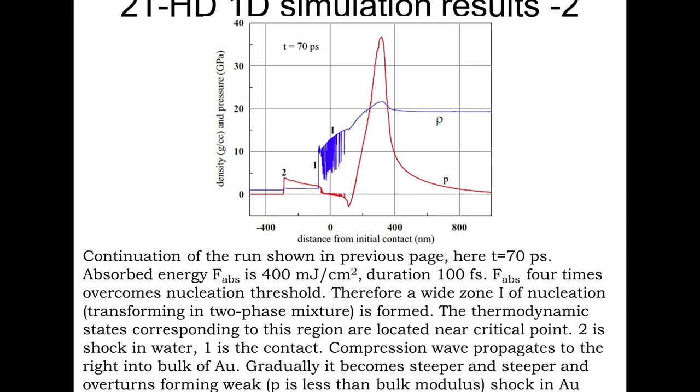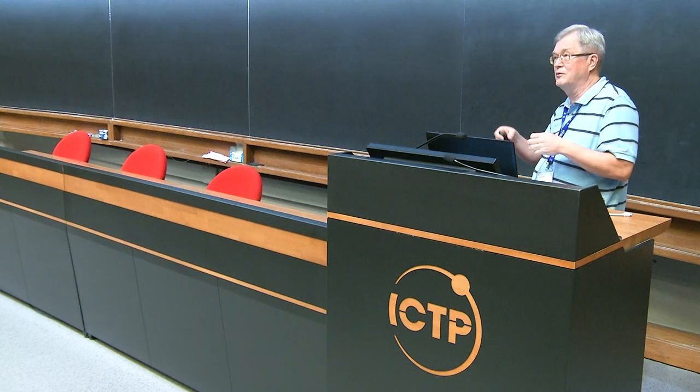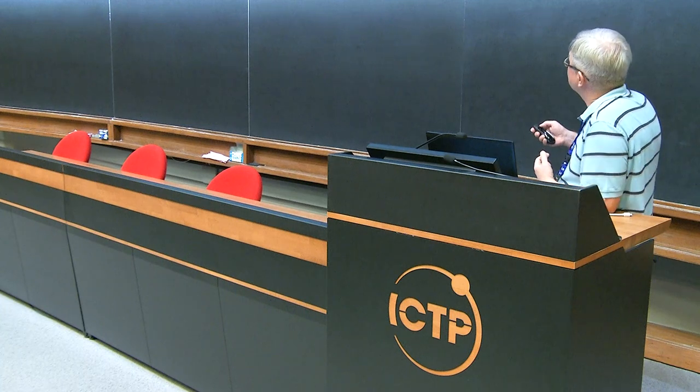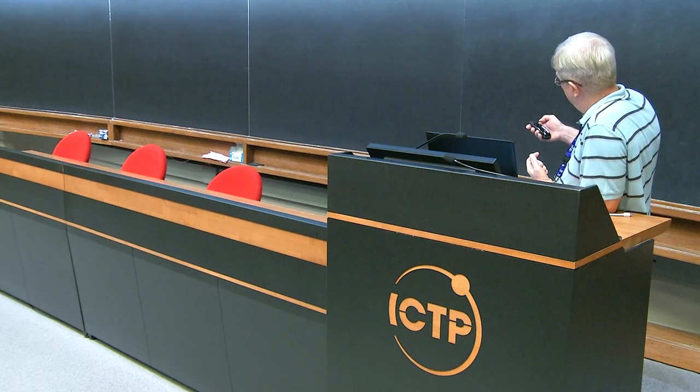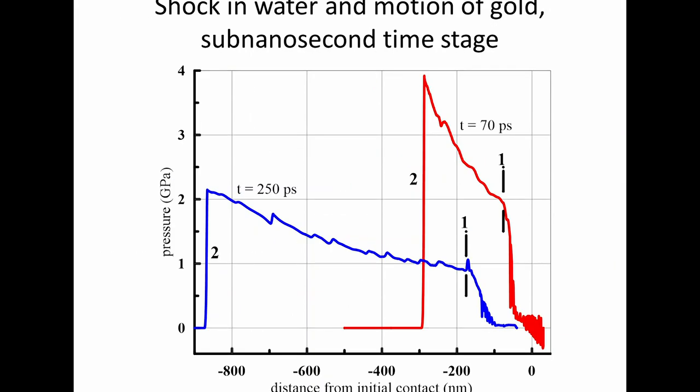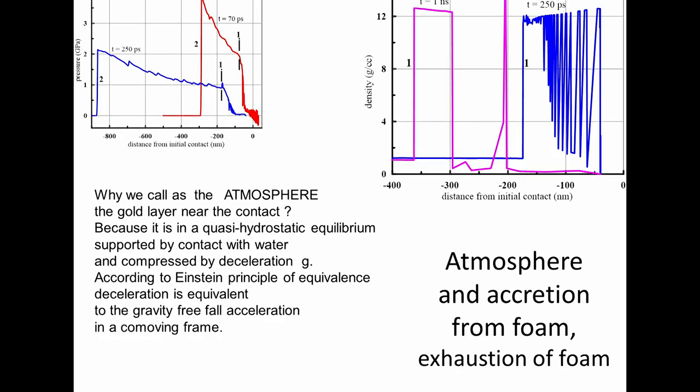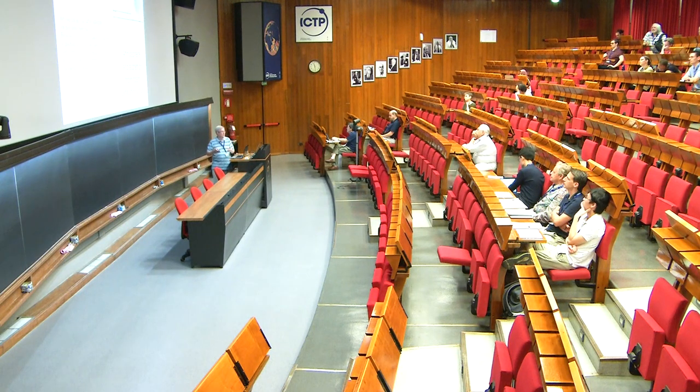When we expand it significantly, it begins to nucleate, it begins to decay to small fragments, and this is the region where it decays. Later in time, this is sub-nanosecond stage, shock goes far away, this is the contact. This is so-called atmosphere. Its motion is decelerated by water, therefore it moves more slowly, but this foam region doesn't know about water. It moves freely, therefore it moves faster than the atmosphere.